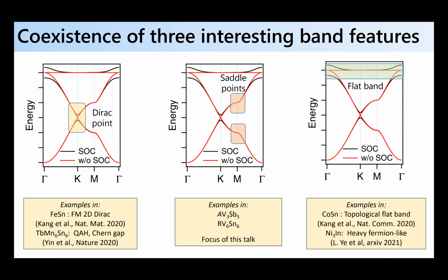As Joe discussed yesterday, there has been a lot of experimental effort recently trying to tune band filling of kagome metals towards this flat band, to bring it to the Fermi level, in which case, in some recent results on nickel-3 indium, a heavy fermion-like phase behavior seems to start manifesting. But the focus of this talk is really trying to explore fillings near this other feature, near the saddle points in the Brillouin zone. These so-called Van Hove points, there are examples where the filling seems to be close to that in the so-called 135 class of materials, or alkali metal, vanadium-3, antimony 5, and the so-called 166 class of vanadium-based compounds, which have a rare earth ion. And I'll talk about two examples of charge order or charge density wave states in each of these compounds in this talk, okay?